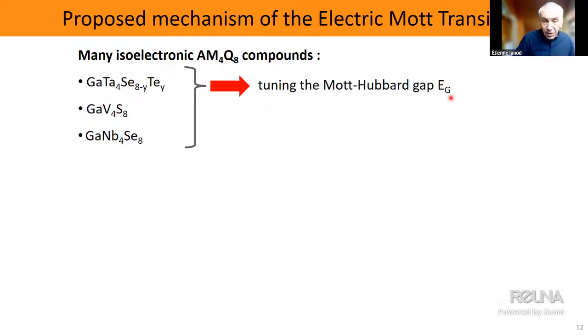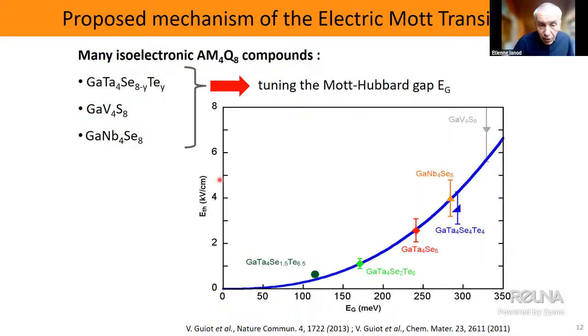So what we have done is study the threshold field that I introduced two slides ago, and we have plotted the evolution of this threshold electric field as a function of the gap of the material. And here is the result. The larger the gap, the larger the threshold electric field. We can describe, roughly speaking, this behavior with a power law, and a power close to 2.5 was able to describe the data.